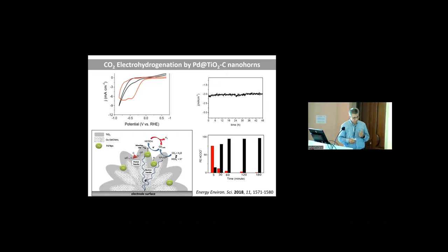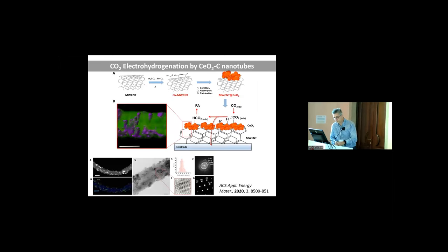So it is a very challenging flow type of reactor, because if you work in batch, you form formic acid, but you also decompose it. The key step is the formation of palladium hydrides. And since cerium dioxide can also form palladium hydrides, we thought, why don't we apply a metal-free system? So just using cerium dioxide on carbon nanotubes, and indeed we succeeded in getting quite a decent amount of formic acid also in this way.